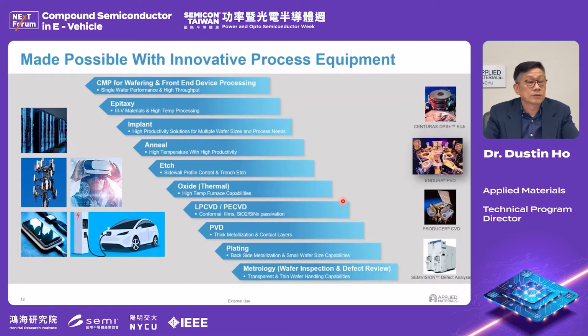So the tools used for the silicon carbide process include CMP for the tungsten, for planarization, and epitaxy, which needs high temperature. We don't offer this one for now. And the implant, because silicon carbide in high temperature implant and annealing needs more than 1700 C high temperature annealing. And the etch is very critical for the trench etch, and you have a thermal oxidation, and then you have the ALD or LPCVD for the conformal film isolation, and PECVD passivation. PVD for metallization, and the backside also plating, and the metrology for inspection and defect is very important too. So we probably offer most of the process equipment tools for this industry also.